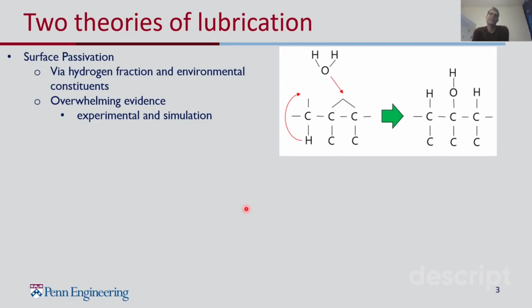The way this works is that high friction in these materials is known in some cases to occur because of interfacial bonding across the interface. So chemical bonds form between the diamond-like carbon and whatever the counterface is. And if you can prevent the formation of these bonds, you can reduce the friction.